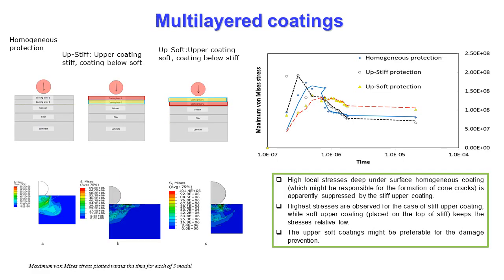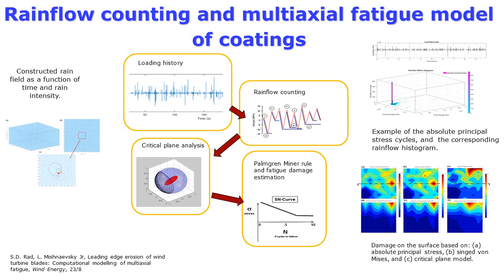Then, stress waves in multilayered coatings under liquid impact were simulated. We compared homogeneous coatings, coatings with a stiff layer on a soft sublayer, and those with a soft layer on a stiff sublayer. It was observed that the multilayered coating with an upper soft layer shows the lowest stresses.